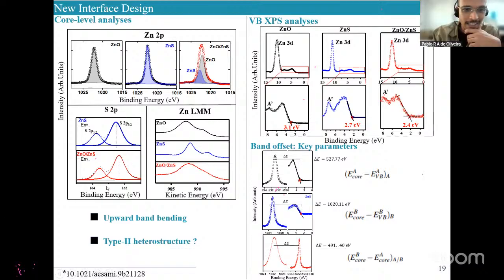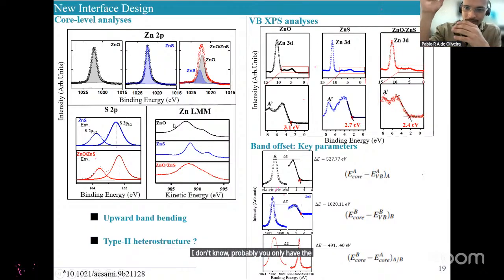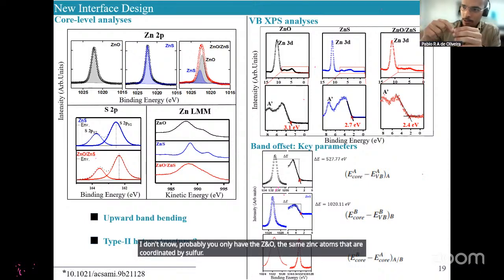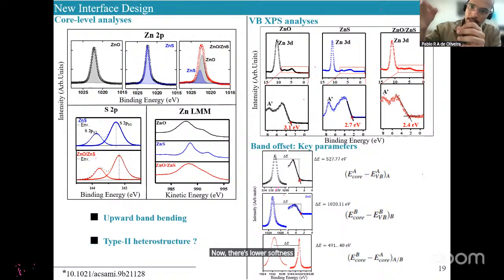The evidence is that the sulfur is not forming sulfate. So I don't know, probably you only have the ZnO, the same zinc atoms that are coordinated by sulfur. Now there's less sulfur available at the surface, and now the zinc is also coordinated by oxygen. So indeed, you have the evidence that we are not forming ZnO and ZnS in a coexistent phase. I would say that. I don't know what point you want to raise.